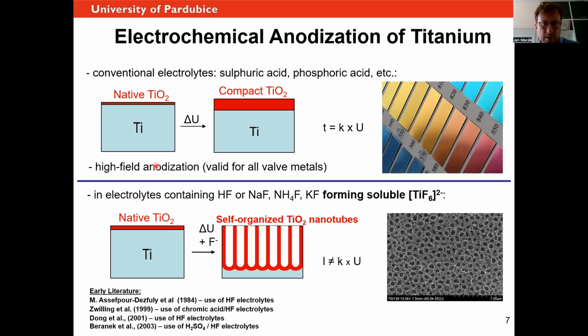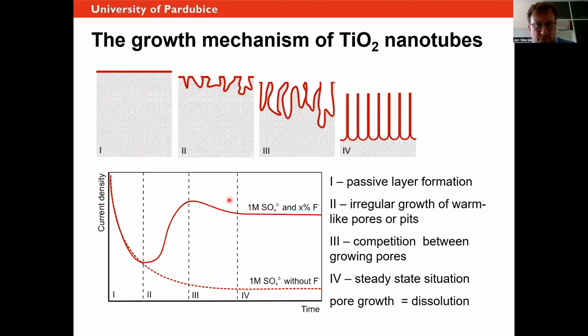And a completely different situation will occur when you add fluorides into these electrolytes. So, for instance, when you take HF sulfuric acid or ammonium fluoride and ammonium sulfate, a new situation will occur. And if you do everything well and you apply the right voltage, the right concentration of fluorides, you will end up with these self-organized TiO2 nanotubes. In the early literature, which comes even from 1984, researchers used HF electrolytes. However, 20 years later, 30 years later, people realized that HF is not really good, not just for security reasons, but also because it's very acidic and it etches these tubes relatively quickly. So you can make them in HF. On the other hand, if you don't rinse it quickly, if you don't wash it properly, you can have some etching of these. So HF is not so good, but in principle, it helps you to grow the tubes.